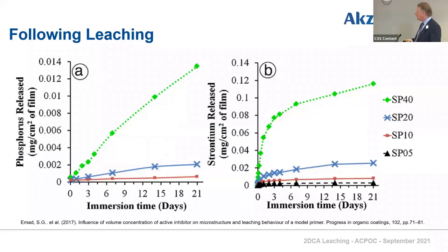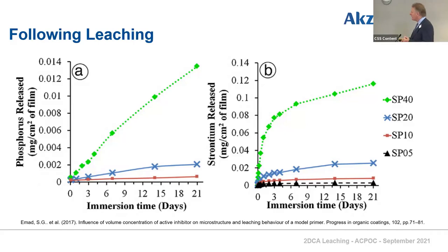That's what I'm interested in simulating, because it's the rate at which those materials release and how they release that determines the corrosion protection. The next speaker's PhD measured a quite complicated corrosion inhibitor, showing the effect at 5%, 10%, 20%, 40% content on the release of different ions. As you'd expect, as you put more in, you get more released, but it's the cumulative release level that determines whether material is still available. Once the cumulative level plateaus and no more material is coming out, you won't protect against corrosion.